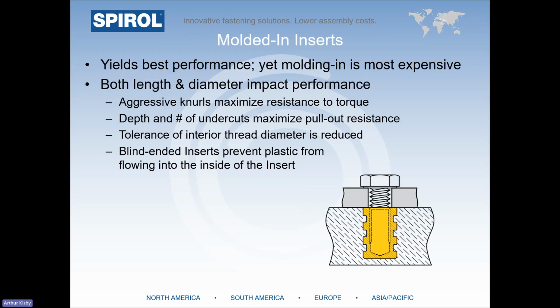For applications that require the highest performance, our molded-in inserts are designed for maximum pull-out and torque resistance. These are often the inserts of choice for thermosets, which are the types of plastics that can't be remelted, as well as plastics with a much higher percentage of filler. The minor thread diameter tolerance on these overmold inserts is tightly controlled to provide a repeatable fit on the core pin that's used during the molding process.